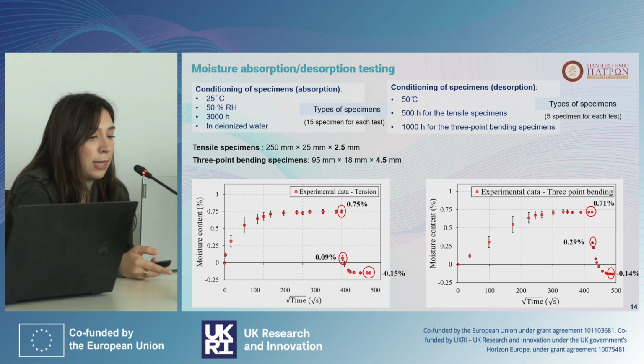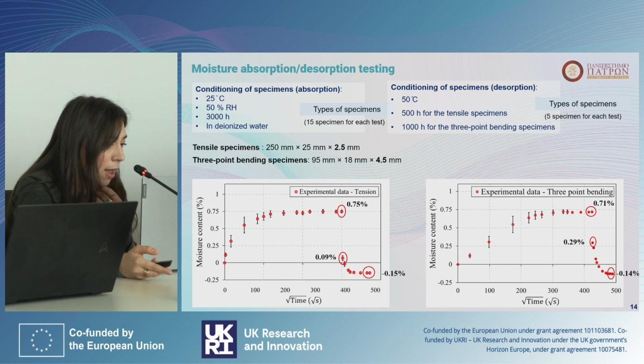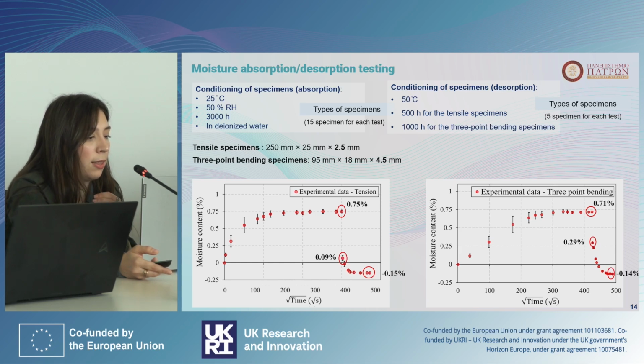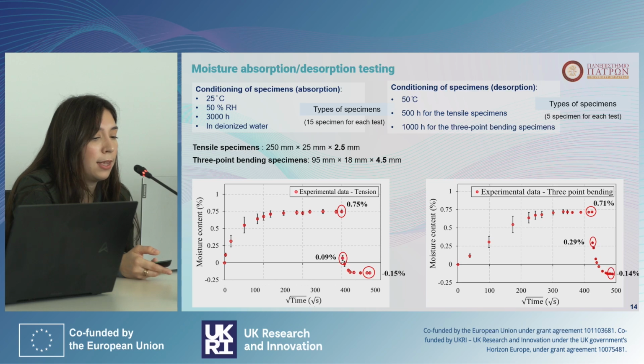The specimens have two thicknesses, which result in different saturation times. And here we can see that for the thinner specimen, the saturation is achieved at 0.75% of moisture absorption, and for the thicker specimen at 0.71%.